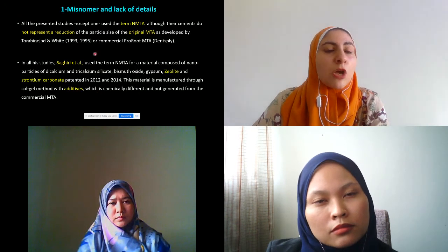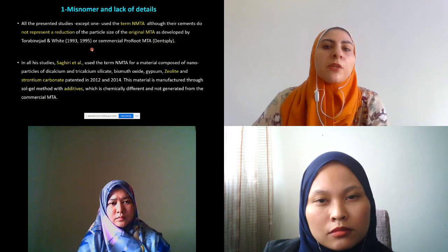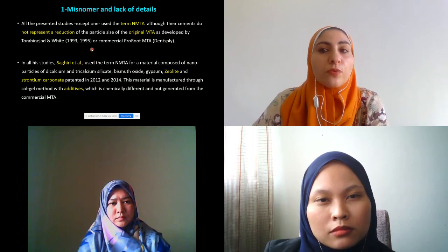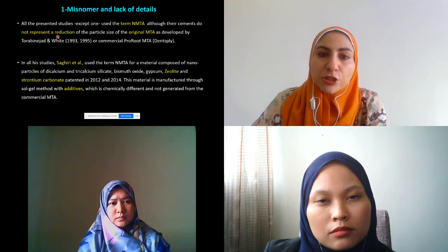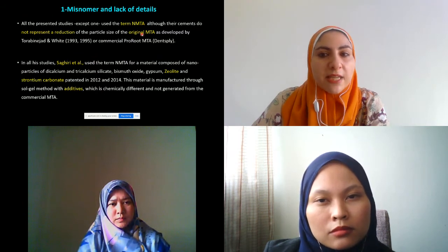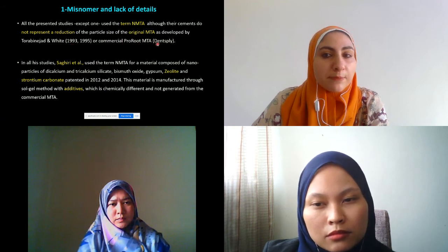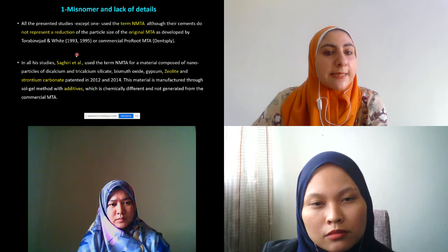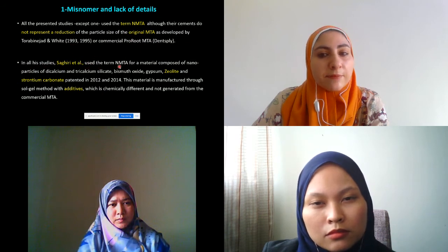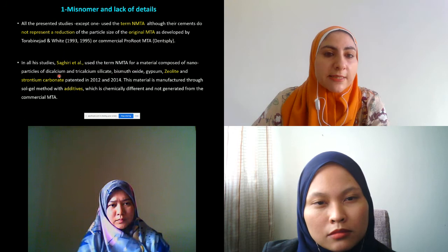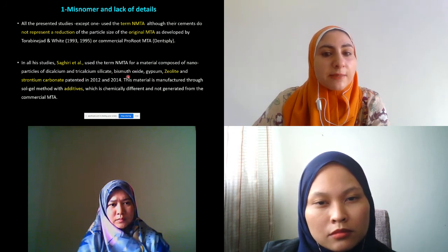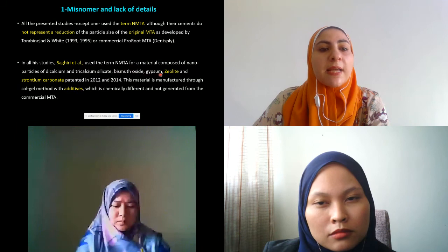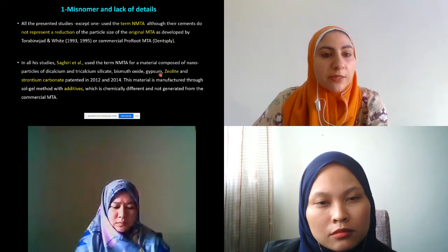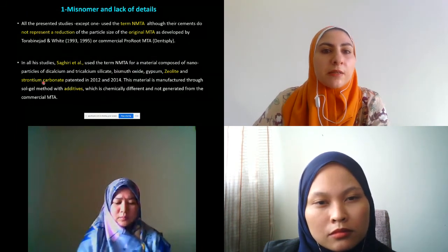Important things to highlight: misnomer and lack of details. All the present studies, except one, use the term Nano-MTA, although their cements don't represent a reduction in the particle size of the original MTA developed by Torabinejad in 1993 or the commercial ProRoot MTA. In all his studies, Saghiri et al. used the term Nano-MTA for his nano-sized cement, which is composed of dicalcium, tricalcium silicate, bismuth oxide, gypsum, zeolite, and strontium carbonate, which is chemically different from the MTA.